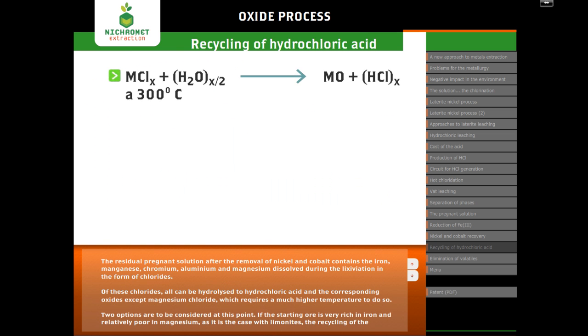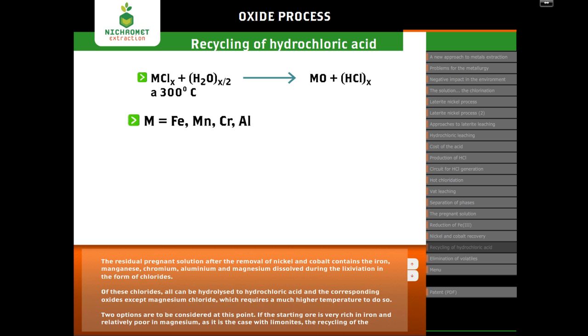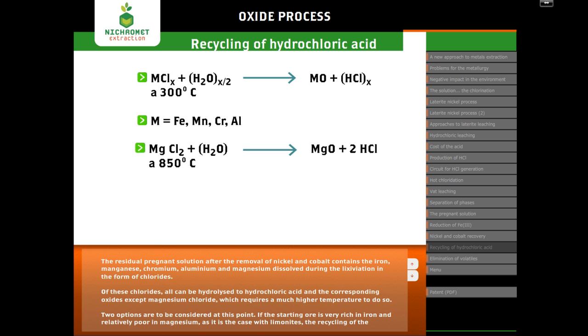The residual pregnant solution, after the removal of nickel and cobalt, contains the iron, manganese, chromium, aluminium, and magnesium dissolved during the lixiviation in the form of chlorides. Of these chlorides, all can be hydrolyzed to hydrochloric acid and their corresponding oxides except magnesium chloride, which requires a much higher temperature to do so. 2 options are to be considered at this point.